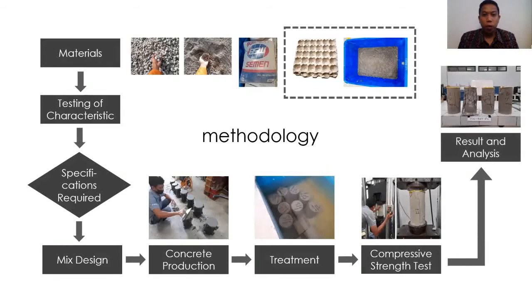For specimens with variation in the addition of egg tray, corrections are made to the water requirement based on the moisture content of the fine aggregate and egg tray. The egg tray must be made into pulp before being mixed with concrete, so that the egg tray can mix well and become homogeneous with the concrete.